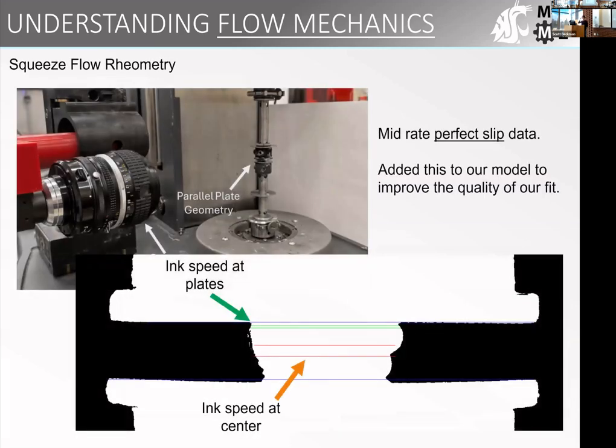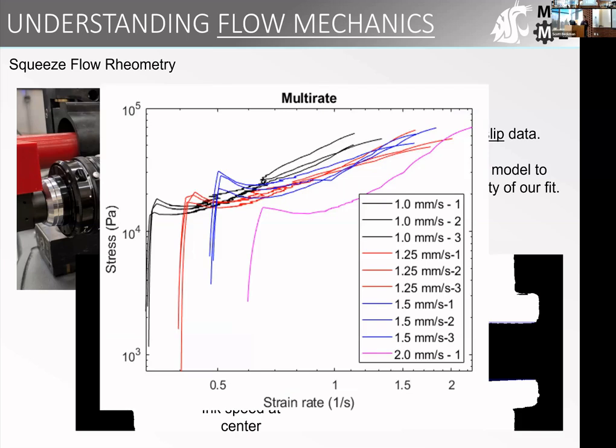We also do squeeze flow rheometry, like I said, where we look at the change in the diameter of the ink at the center of the filament, as well as at the plates, so that we can best monitor the shape of the material as it's compressed. And this method looks at perfectly slipping material. So we're under the assumption that our materials are undergoing 100% slip with no shear flow. So the exact opposite of our rotational rheometry method. And we can confirm that by looking at the flow rate data that we get from squeeze flow, where if we have overlapping lines in our flow curve, that says slip flow is happening.